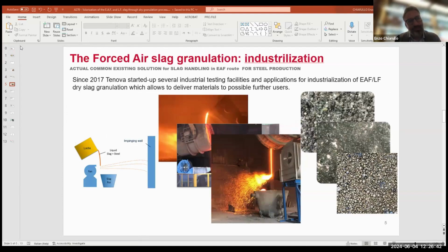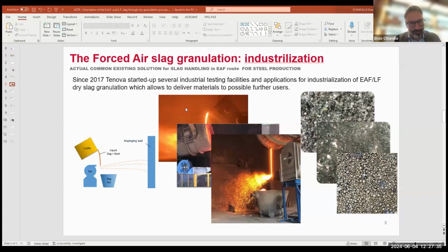Just to say that since 2017, Tenova has started up several industrial testing facilities in the world of steel. We have technology applied in line, where, as you can see here, an automatic tilting device is applied to a slag pot in order to perform the slag pouring, or, as in this case, a liquid flow that is broken by a fan. In this case, the slag is moved by a crane. Different conditions apply for different kinds of slag and different grain size. Just to have a look at some of the results that we obtained, some of them are represented on slide number 6.